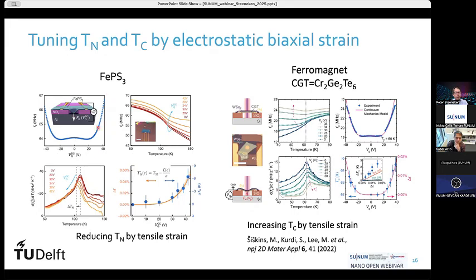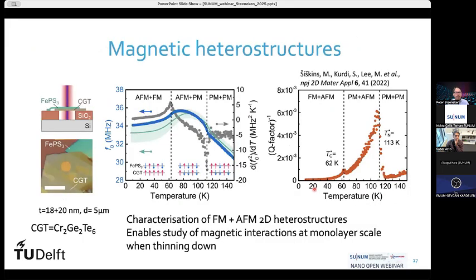For the antiferromagnetics, we saw that this Néel temperature is going down, whereas for a ferromagnetic 2D material, like this chromium germanium telluride, you see it going up. So this nanomechanical resonance presents a way to study these 2D materials and how they behave under strain.